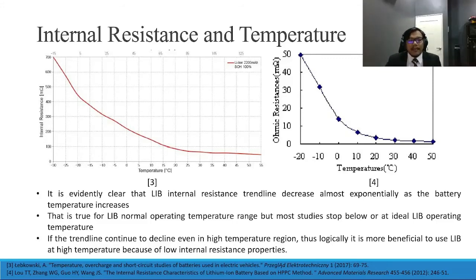So he made the internal resistance against temperature, where he plotted a varying temperature from negative 30 Celsius to 55 Celsius. Noted that internal resistance is high at cold temperature at negative 30 and drops very low at high temperature, 55 degrees Celsius. And on the right is a study conducted by Lou in 2012. So they have a similar pattern. Okay, it is evidently clear that lithium-ion battery internal resistance trend line decreases almost exponentially as the battery temperature increases.